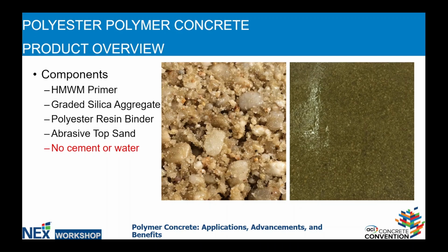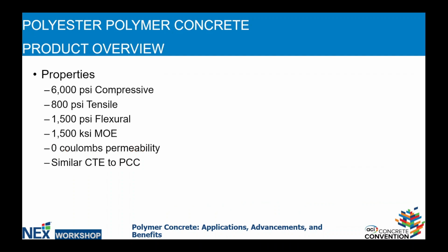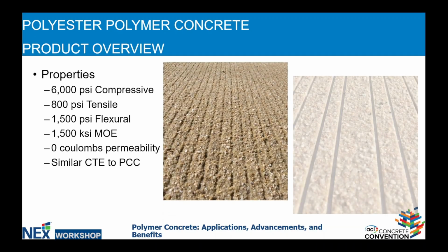On the left side, you see the aggregate that is pretty fresh out of the mixing truck, but then after it's finished and applied in the field, it will have a glassine type finish, which ultimately receives the oven-dried silica sand broadcast, and we'll see that in a moment. Some of the properties of this type of product include formidable compressive strengths at 6,000 psi, 800 psi in tensile strength, 1,500 psi in flexural strength, 1,500 ksi in modulus of elasticity, 0 coulombs in permeability, and a similar coefficient of thermal expansion to Portland cement concrete itself.